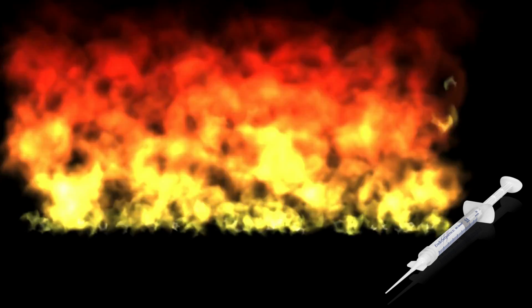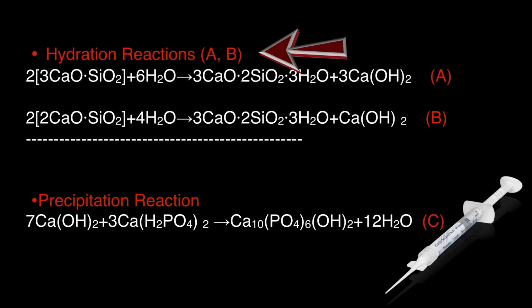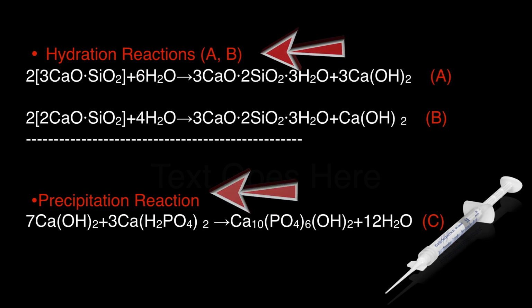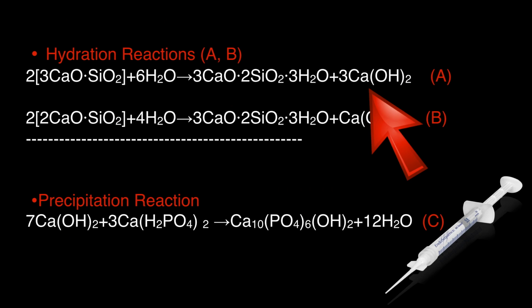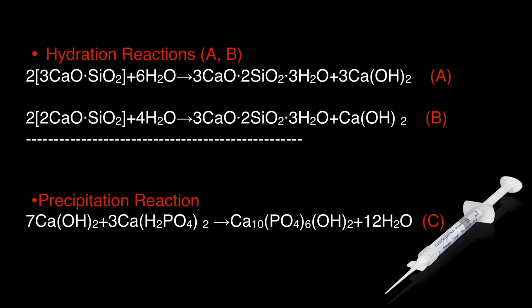So if you look at all the bioceramics, they have a hydration and a precipitation reaction. In the hydration phase, the calcium silicate picks up the water molecules. In the case of the BC sealer and these nanoparticulate pure bioceramics, they pick it up from the surroundings because obviously it's used in vivo in an environment where we're 75% made out of water. And then the water reacts with the calcium silicate and produces the calcium hydroxide. And from that, we can immediately tell that the material is going to be hydrophilic. So you've got a hydrophilic material that also has the ability to be antibacterial.